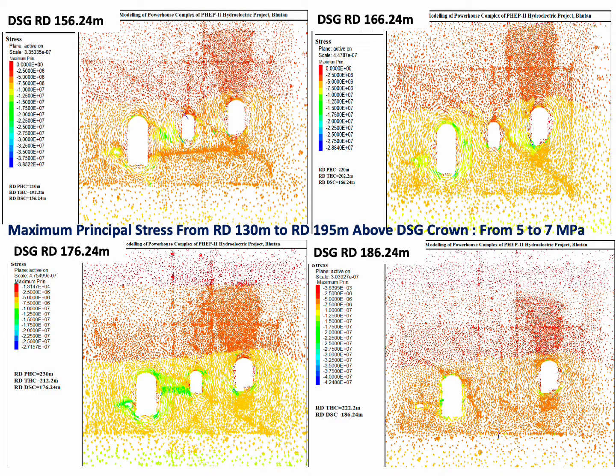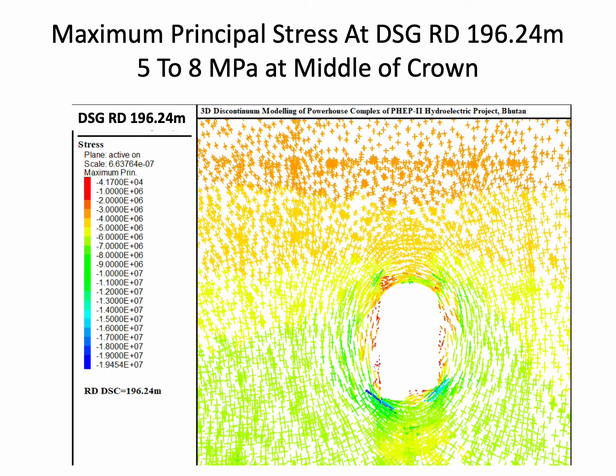At different reaches 156, 166, 176, 186 and beyond, similar conditions of stress concentrations are seen up to 100 meters of height above the crown, which were having major principal stresses of the value of 5 to 7 MPa, which was much more than the UCS of the rock mass itself of 2 MPa. So if we see near around the crown, they were in the range of 5 to 8 MPa at middle of the crown. This 5 to 8 MPa range, green colors, yellow colors, they are there in the near vicinity of the crown. Middle of the crown at RD 196.